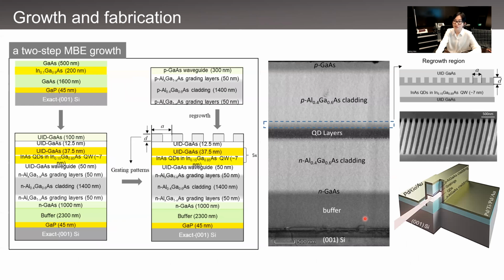So the DFB structure was grown on an on-axis gallium arsenide on silicon substrate by a two-step MBE process. So the first growth stopped at this 100 nanometer UID GaAs layer on top of the active layers, and then a uniform first-order DFB grating was dry etched into this GaAs layer with an etch depth of 50 nanometers. So here is the SEM image of the surface grating, and the grating quality and the following pre-regrowth surface treatment are very important, and they are stringently controlled to achieve high-quality regrowth of the rest of the laser structure. And after that, the material was processed into deeply etched waveguide structures.